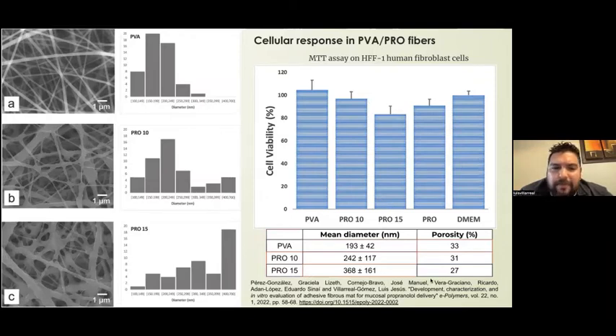What I'm trying to say here with these 2 examples of our experiments is that if you use the correct polymer for a certain application, you will not have any tissue response. Of course, you will have a tissue response, but it will be a slight one and will not alter the health of the tissue where you are applying these systems. These fibers are thinner. As you can see, the fibers are 200 to 300 nanometers, thinner compared with the polycaprolactone fibers. And you can also control the porosity.